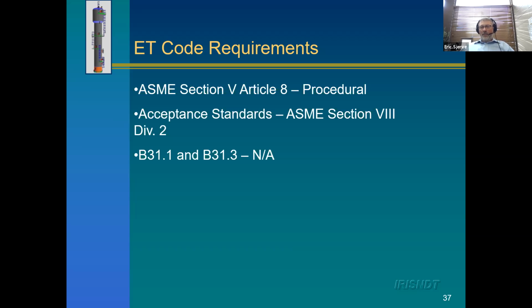Most of the components we use in the industries we have in Alberta are thicker, and eddy current just doesn't penetrate thick. If you can go 2.5, 3 millimeters deep into a part, that's really good. You're doing well with eddy current if you do that, but that doesn't cover much of what we have here. So it's used for heat exchangers for the most part, and we just don't see it in other parts of industry in Alberta because it just doesn't have the ability to penetrate the kinds of depths we have.